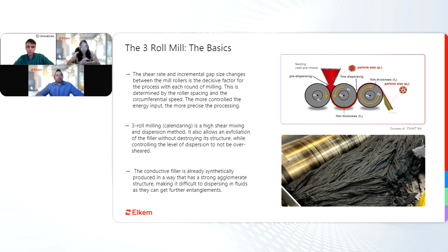These carbon nanotubes tend to be really strong agglomerate structures that come pretty entangled and are already more difficult in dispersing in fluid. So using a mixer or other dispersive methods may not be as successful compared to a 3-roll mill.